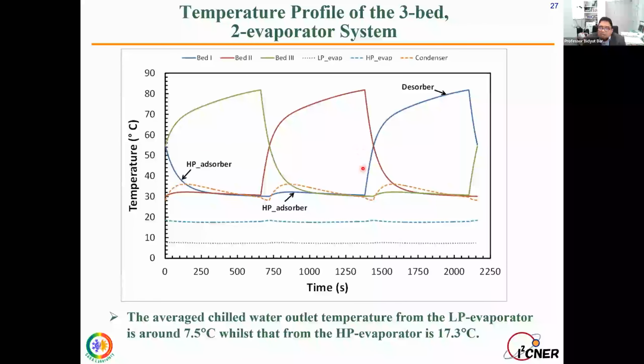So what kind of outlet are we getting? The average chilled water outlet temperature from the low pressure evaporator is about 7.5 degrees. And from the high pressure evaporator we are getting about 17.3 degrees. So we can use this temperature, like from 16 to 22, for the process cooling application, and this is very good for our room cooling applications.